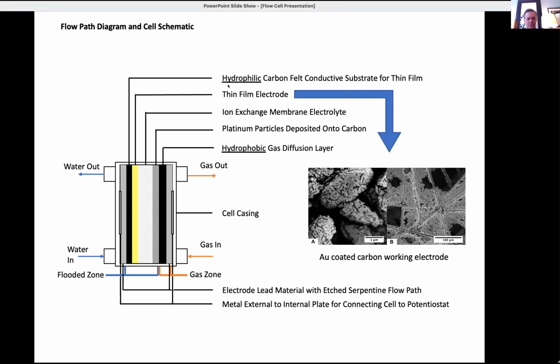So we have our thin film electrode here. What we do is we flow our solution through here, and we have a special membrane here, which is a proton conducting membrane, which gives us constant pH. And this polymer membrane substitutes for the electrolyte solution. And it can be regenerated by a counter electrode here, which can split the water and regenerate protons for the replacement of any of the protons here that get consumed in the reaction. It can regenerate the membrane. So you are at constant pH, which is a requirement for these.